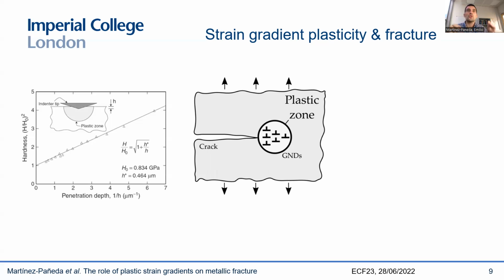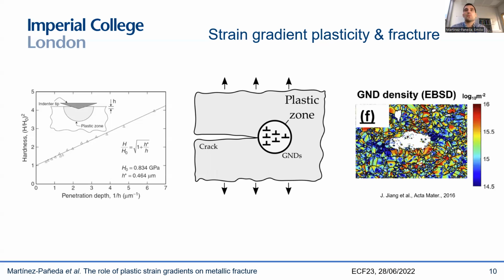And as I said before, those GNDs are going to act as obstacles to the movement of the statistically stored dislocations and are going to elevate the stresses near a crack, in that region near the crack where plastic strain gradients are significant. And in fact, nowadays we can measure GND densities ahead of crack tips and inclusions, and what we see from experiments is that GND densities are very large and dominate material behavior near inclusions and cracks.